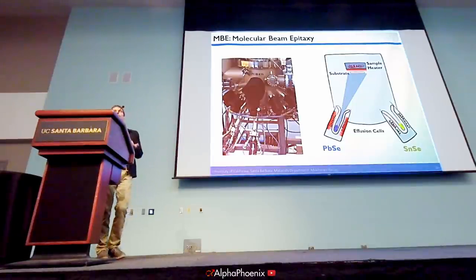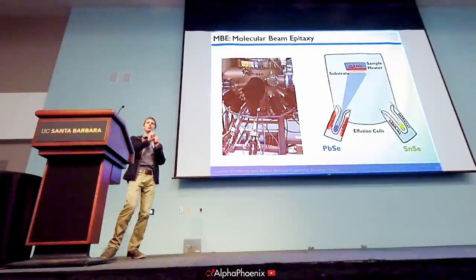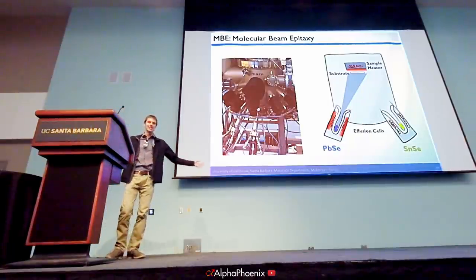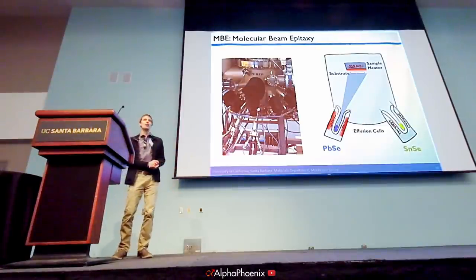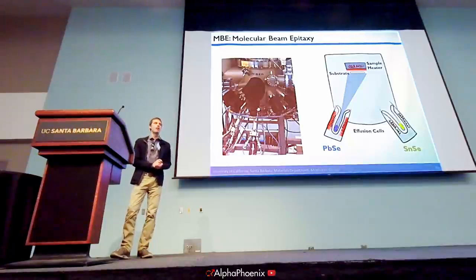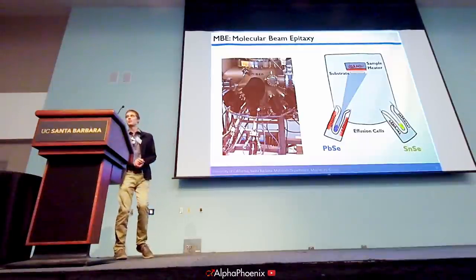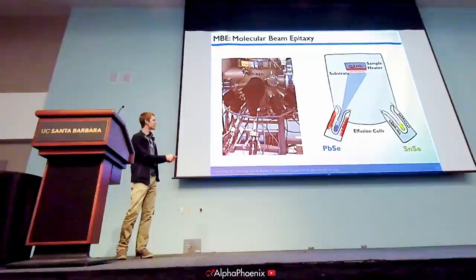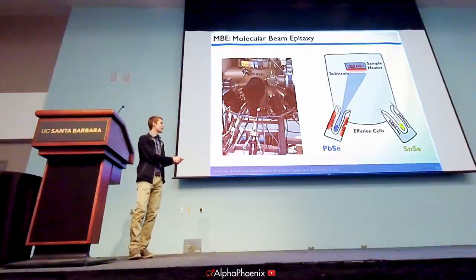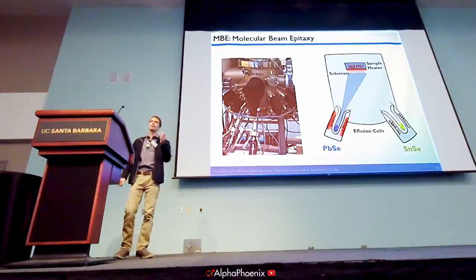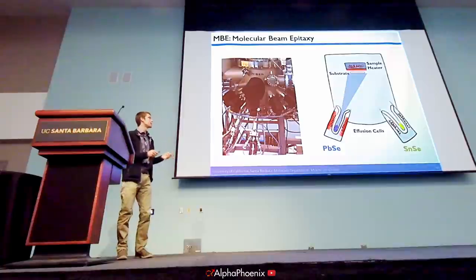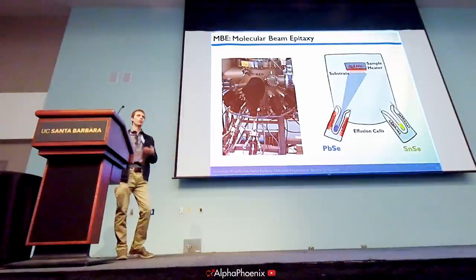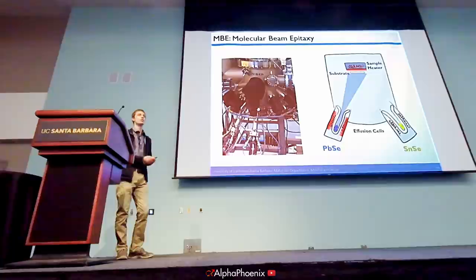If you tried to do this in air, it wouldn't work. The mean free path of a particle flying through air is something like 70 nanometers. This chamber operating under ultra-high vacuum has a mean free path on the order of kilometers — and the eagle-eyed viewer may notice that this chamber is not kilometers across — which means the vast majority of lead selenide molecules evaporated from the crucible travel to the substrate in a straight line without running into anything. That gives us really precise control over the chemical species that land on the substrate. There's no ambient atmosphere to oxidize a free surface; in an MBE you have complete control over the interface.